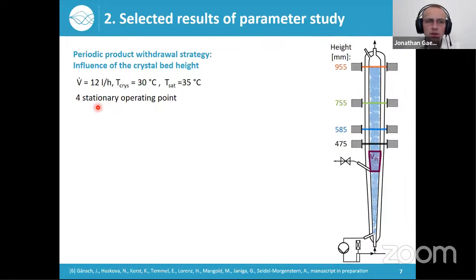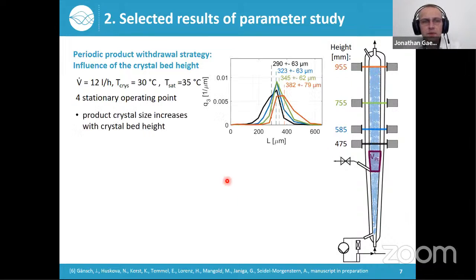And finally, we're getting 4 different stationary operating points, which mainly differ regarding the maximum height of this crystal bed. The volume of withdrawn product suspension was constant for all these operating points. We are just changing the height of the crystal bed. And here we could observe that first our product crystal size increases with this crystal bed height, which is nice to know.